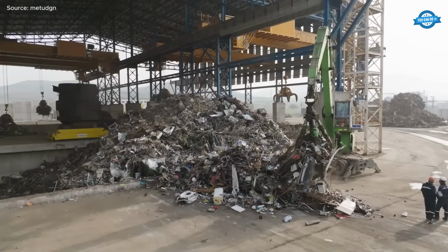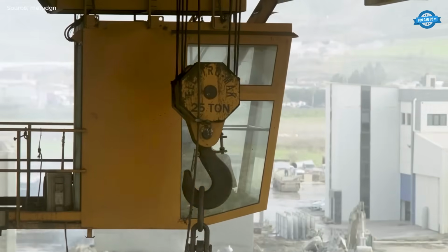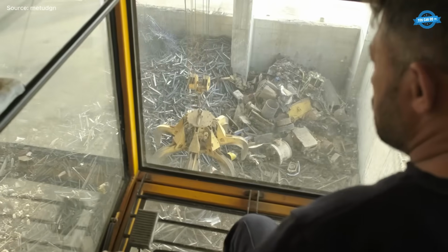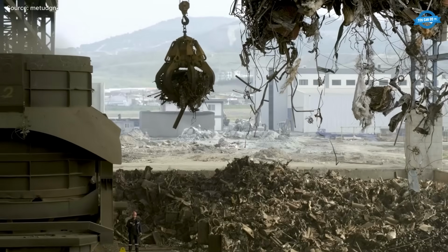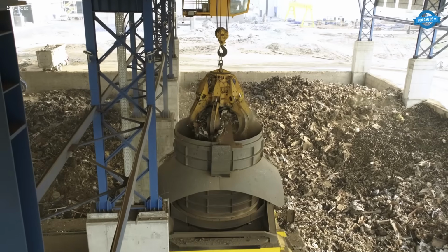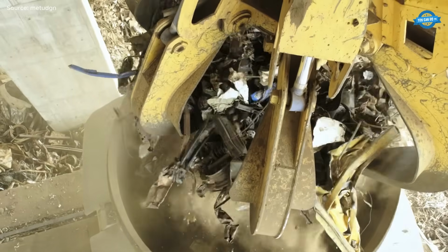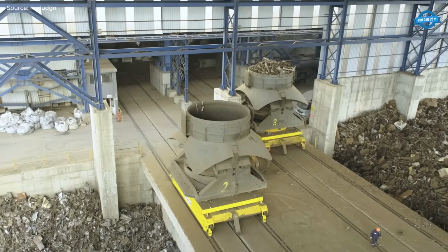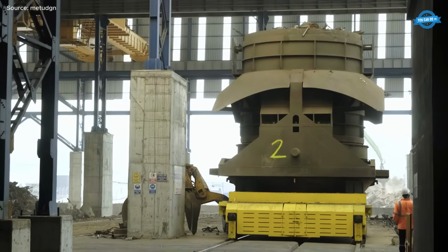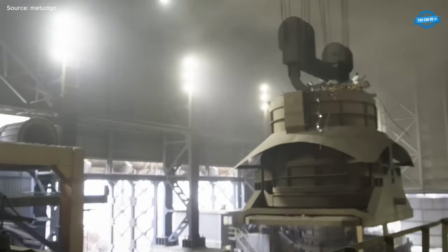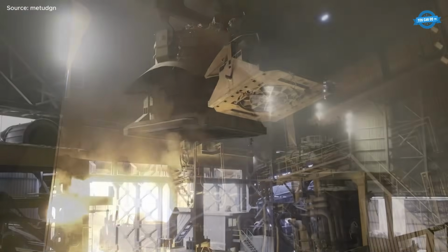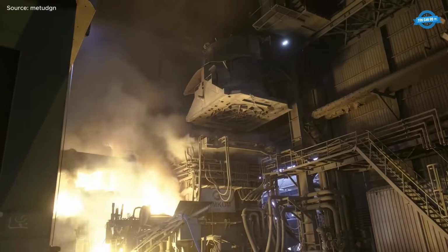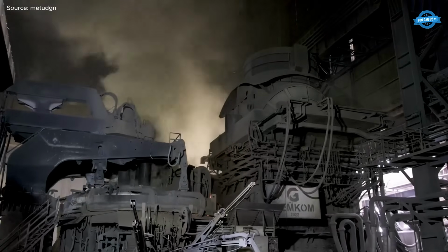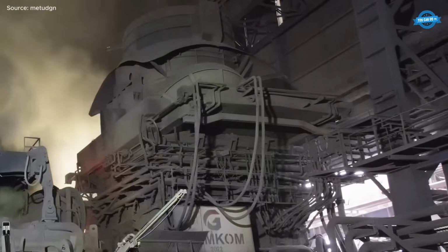At FESCON 2023, the Continuous Preheating System for Electric Arc Furnace (EAF) operations drew significant attention for its energy efficiency and performance enhancement. This system utilizes recovered off-gas heat to preheat scrap metal up to 600 degrees Celsius before charging, significantly reducing tap-to-tap times and lowering electrical energy consumption per ton.